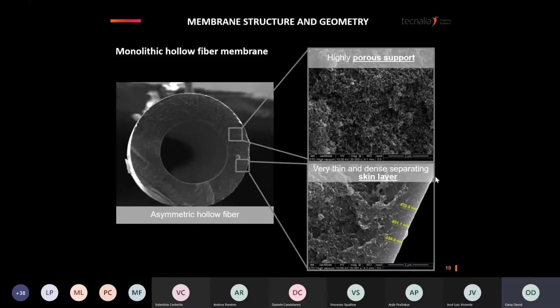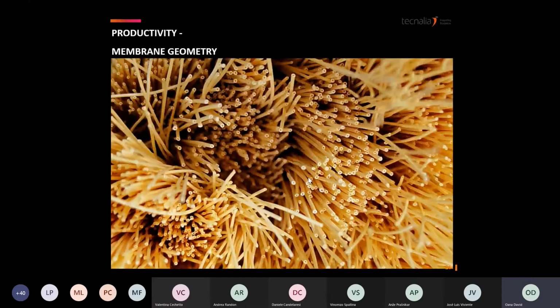Then here I show an example of a monolithic asymmetric membrane in the geometry of a hollow fiber. Here the outer diameter is about 500 micrometers maximum. And you can see the top selective layer on the outside, and there is a smooth transition from a dense top layer to the porous sublayer, and everything is made from the same material. When it's possible, this kind of geometry and structure is desired, but not all polymers can be processed this way. Here I show a picture of hollow fiber membranes.